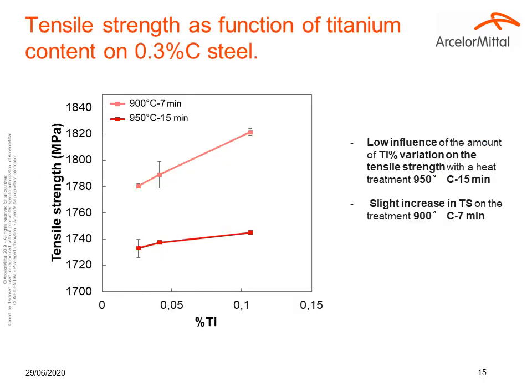We begin with the evolution of tensile strength as a function of titanium content. There is a low influence of the titanium content on the tensile properties with a heat treatment of 950 degrees during 15 minutes, but a slight increase for the treatment of 900 degrees during 7 minutes. The effect of the amount of titanium content on tensile strength is not very high, but remember that titanium may go into particles because it protects boron from nitrogen, so we can look at the population of titanium nitride inclusions.